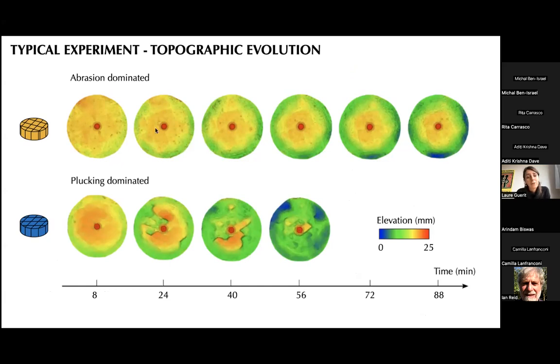The topography is quite smooth, and you can see that erosion is mostly located on the edges of the disk. This is typical of abrasion-dominated experiments. At the bottom, the network was forming diamonds, and you can observe that this time erosion is not at all symmetrical because we have removal of blocks almost anywhere on the disk, so we have plucking.